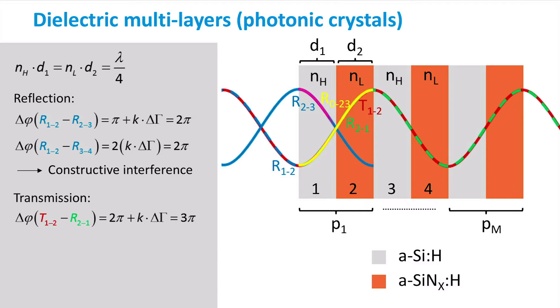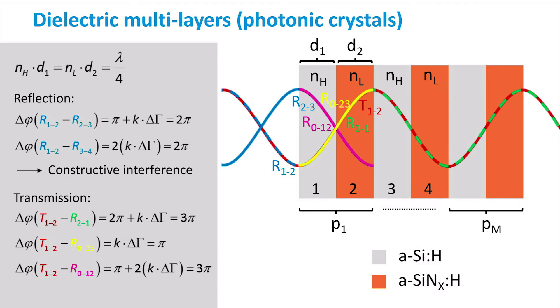Also, the reflections from the front surface — wave R₁₂ denoted by the pink line, and wave R₂₃ denoted by the yellow line — exhibit a phase shift of an uneven number of π's with respect to the transmitted wave at the 2-3 interface. As such, the transmitted wave and the waves that undergo an even number of reflections will exhibit destructive interference. This means that at each interface between the dielectric layers, reflection is maximized due to constructive interference and transmission is minimized due to destructive interference.